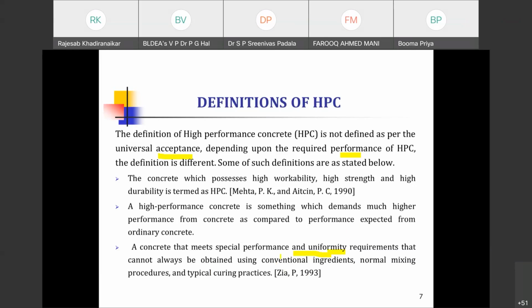and it has a low porosity, hardly 1 to 3%, and a proportionately lower percentage of capillary porosity, that is only 10% compared to 20 to 28% in case of conventional concrete. So these features make it distinct from your conventional concrete. That is why it is concrete that meets special performance and uniformity requirements that cannot always be obtained using conventional ingredients,